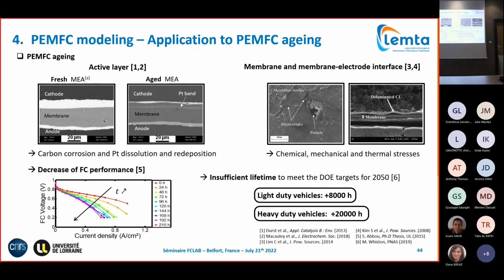Another component is the aging of the membrane due to chemical, mechanical, and thermal stresses. The tricky point with membrane aging is that you won't have any significant impact on your performance until pinholes and cracking happen, and this will, in the worst case, result in a direct stop of your fuel cell.